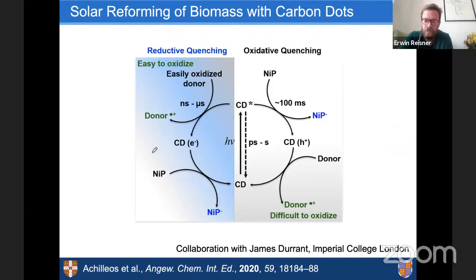What we believe is really essential, again, goes back to kinetics. So if you take these carbon dots and you photoexcite them, you have different photoexcited states and they relax on a time scale from picoseconds to seconds. So there are some very long-lived systems in there. If we have an efficient electron donor or a system that's easy to oxidize, then this will be the preferred substrate. So we look at the reductive quenching process where the donor, like triethylamine, for example, is being oxidized.